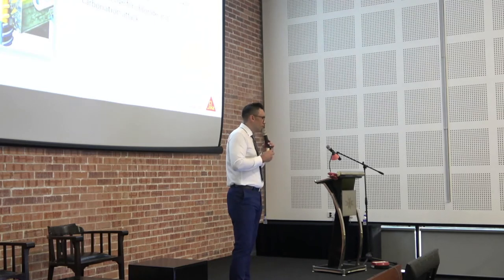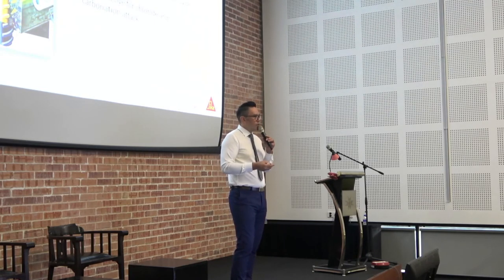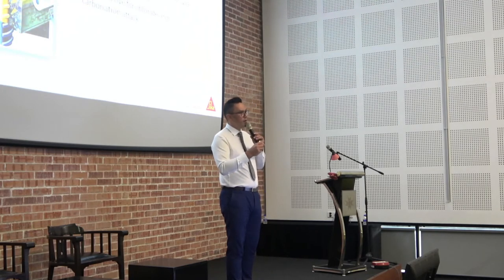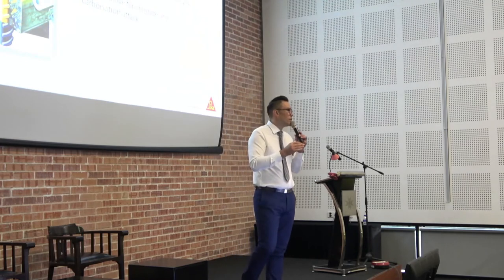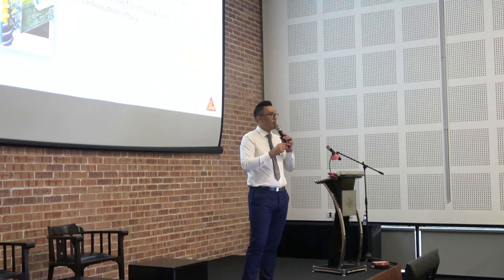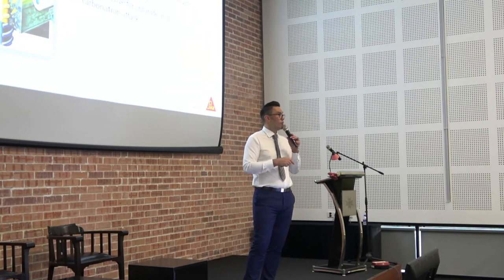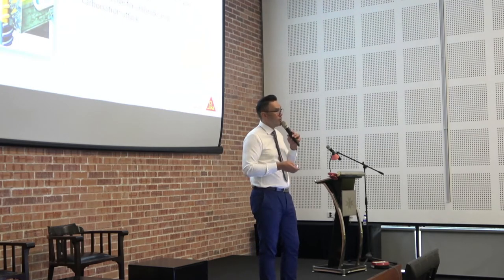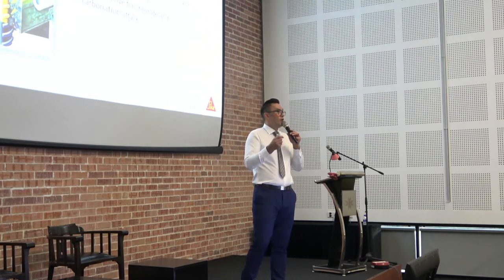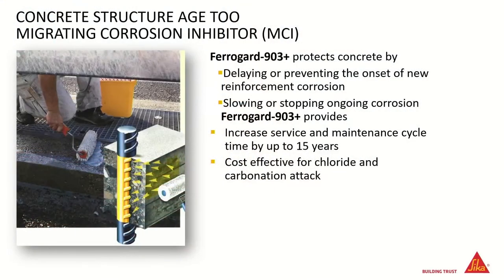And when we talk about a passive layer of reinforcement, when you first cast concrete against reinforcement, the high alkalinity, the pH of concrete, usually 12, 13, something like that, that high pH will instantly form a passive layer around the reinforcement. And that passive layer will stop immediately that reinforcement from corroding any further. And it will stay like that, inevitably forever, if it's not acted upon. So that's why we have such a good marriage between reinforcing steel inside concrete in a high alkaline environment, because the corrosion doesn't go. The reason the corrosion kicks off is because we might have a defect or a flaw or a crack and moisture, and something's been able to get in and upset that balance in the alkaline environment.